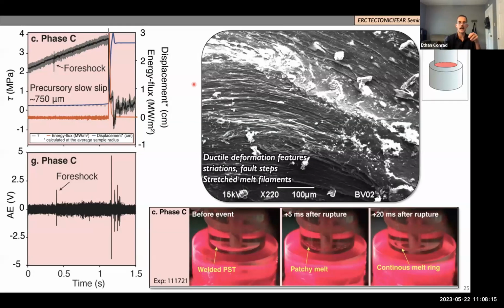Yeah, and that might be maybe because you have this more chunky patch that could be a discontinuity in the flow and disturbing the stretching of these filaments. I think that this gets quite complicated when you're starting to interpret these stretched out filaments. But that's a really interesting point. And the slip rate is less as you move in, so presumably the temperature is lower toward the interior. Yeah. You would think so, yes. And some of the temperature is going to be conducted pretty rapidly throughout the material. But yeah, that initial spike is going to be obviously the maximum at the maximum outer radius, and then less in the inside.